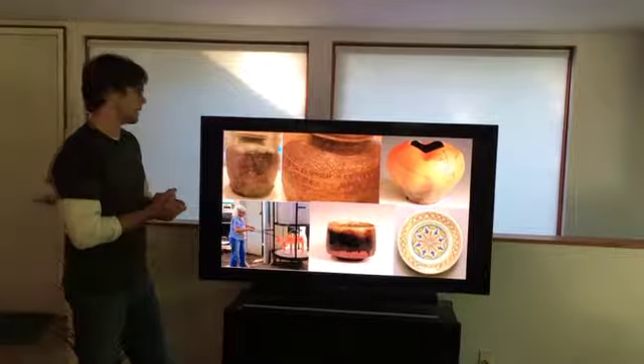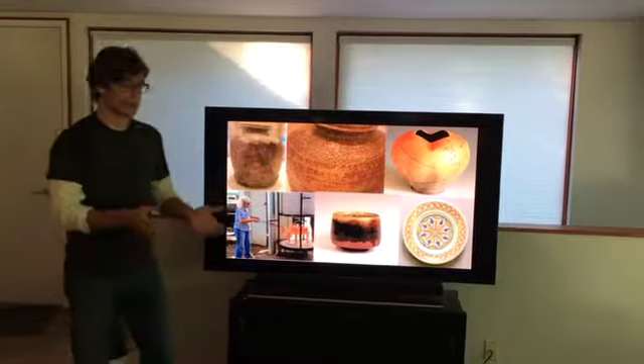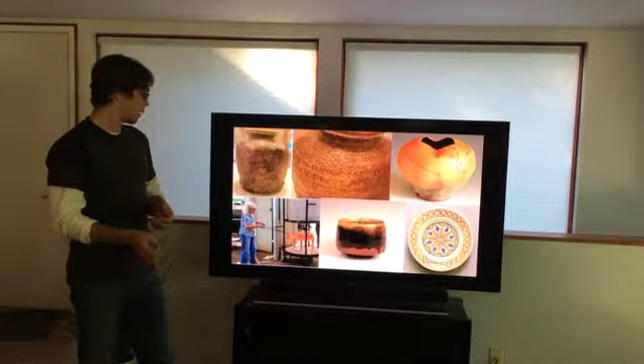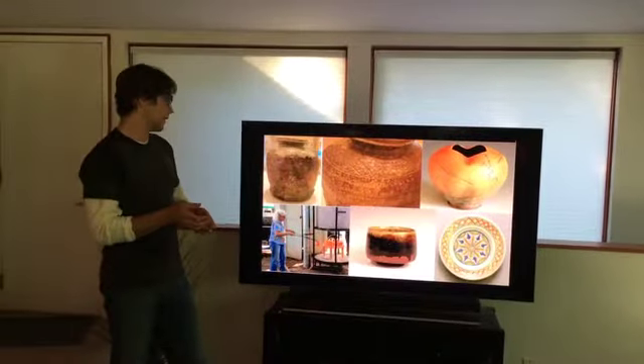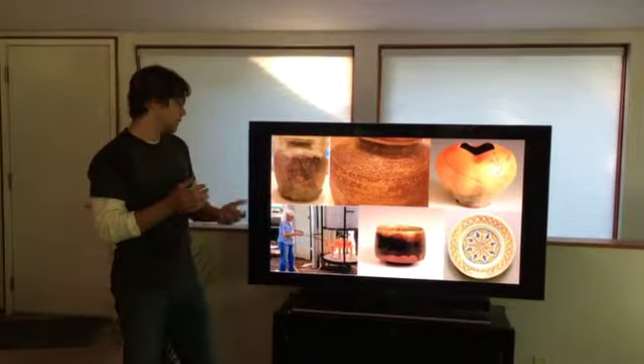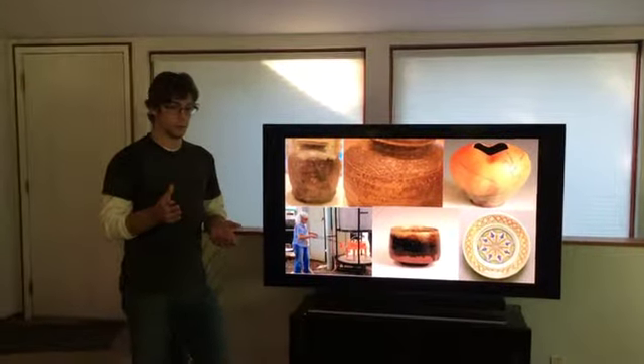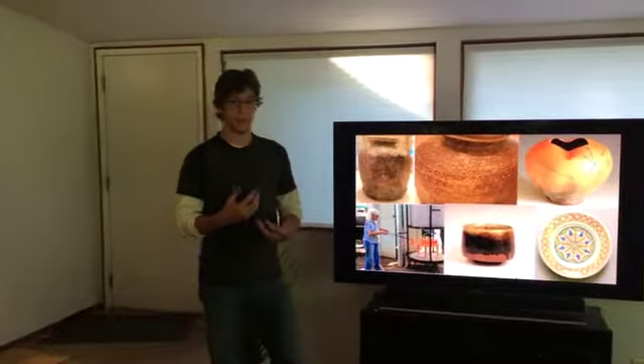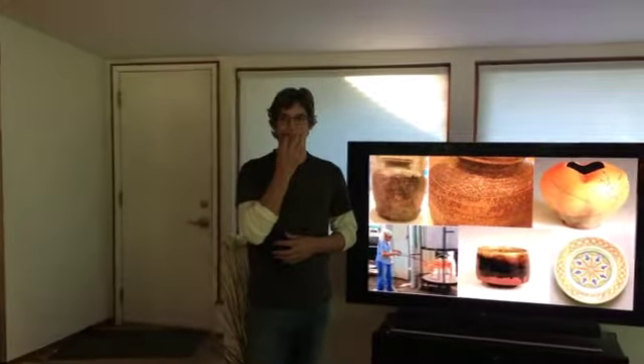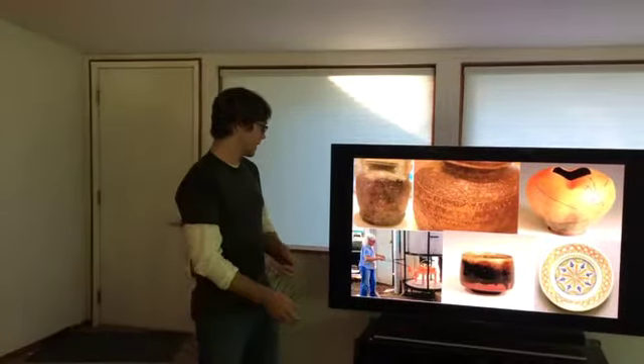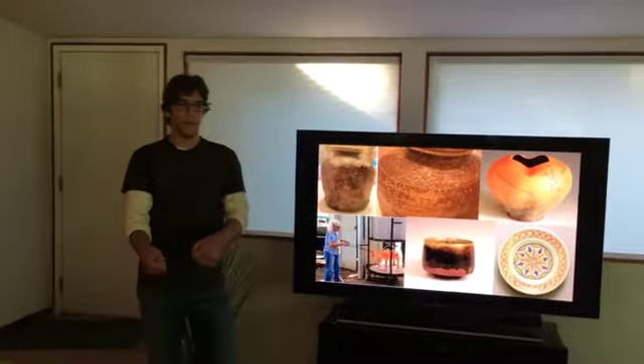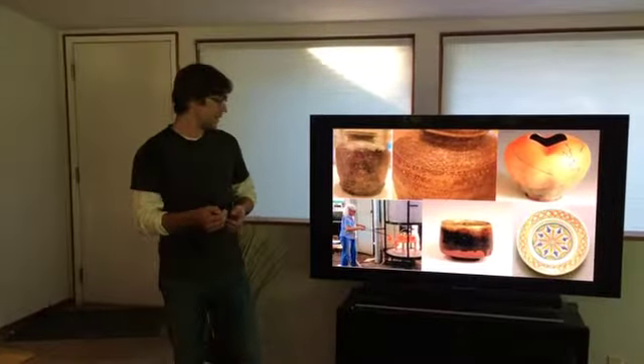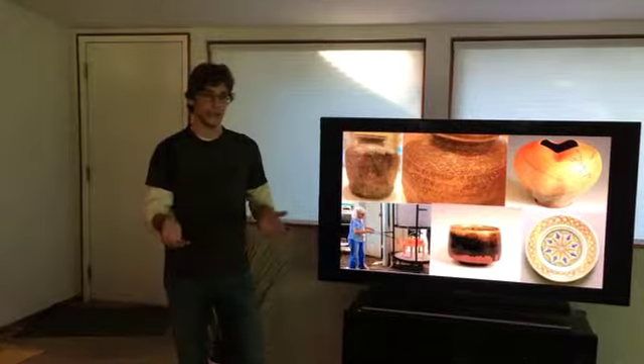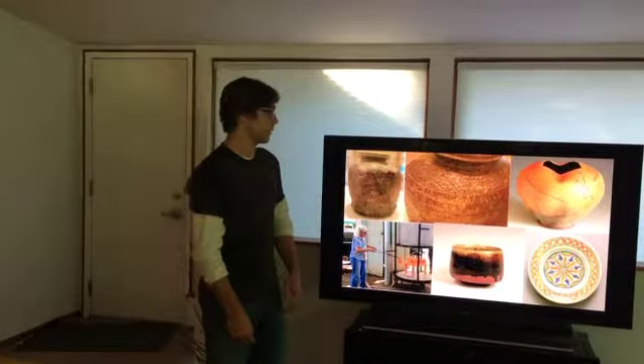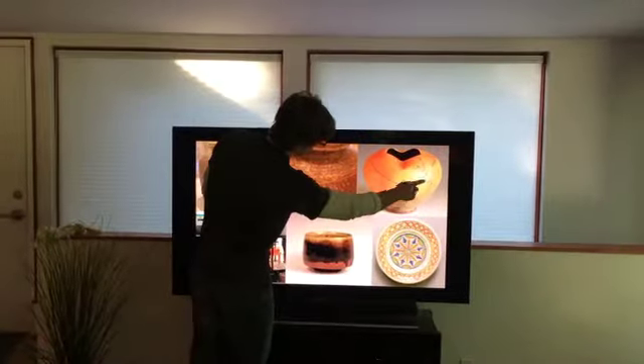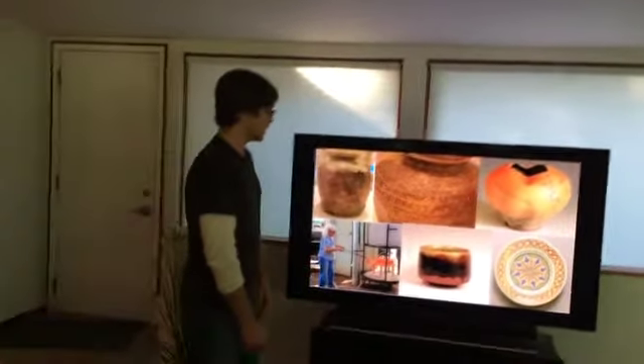Now, raku is a style where the pot is pulled out of the kiln while it's glowing red and probably in the ballpark of 1,800 degrees Fahrenheit. Now, safety practices on this vary a lot. At my high school, we would dress up in worn out firemen's outfits and be completely decked out. We would have fireproof visors and everything, and then we'd use a long pair of tongs to pull them out, put them into a trash can that had newspaper in it. The newspaper would ignite and the carbon would be used to reduce and color the glazes, which gives you these dark lines here, which aren't cracks but are actually just colorations from carbon.